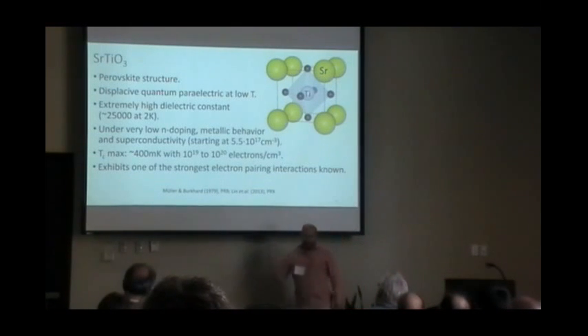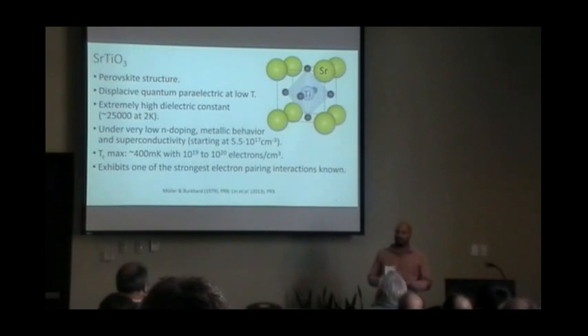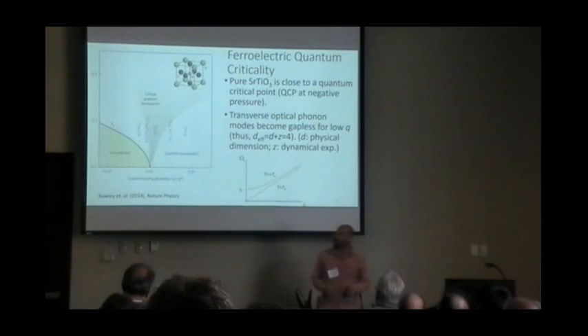So why should anyone be interested in a superconductor with such a low critical temperature? Well, as a matter of fact, due to its diluteness, it is generally thought to be the superconductor with the strongest interaction between the electrons of all the superconductors. So if you could create a material which shows the same type of interaction at higher temperatures, that would be spectacular. And if you reached the normal electron concentration, you would easily be in an area of room temperature superconductivity. However, it's doubtful.